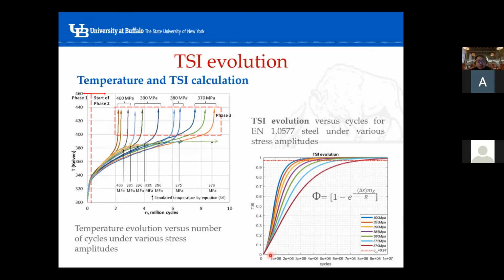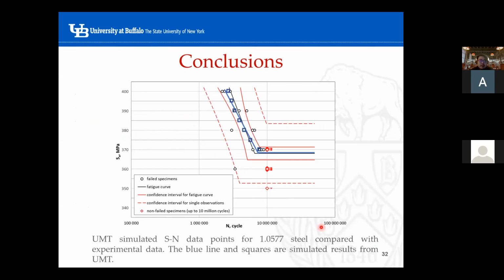Finally, this one will be the thermodynamic state index evolution from 0 to this given number. So we can use the stress amplitude versus the number of cycles to reach failure to again reproduce an SN curve, and this time we can see our SN curve in this line.